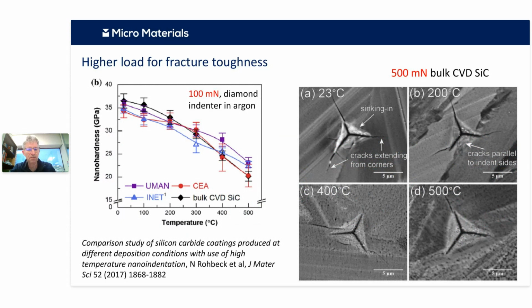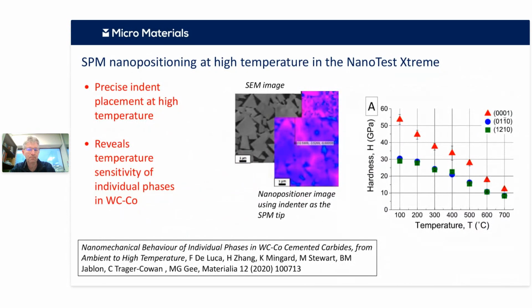So an alternative approach to, as James was talking about, the chevron notched beams. So these nano-positioning stages allow you to accurately position and target specific phases. So in this case, there's some work done by MPL where they've indented into certain phases, and they know exactly which phase is which, and then they can see how the mechanical properties of the different phases in the material, in this case it's cemented carbide, vary as a function of temperature.